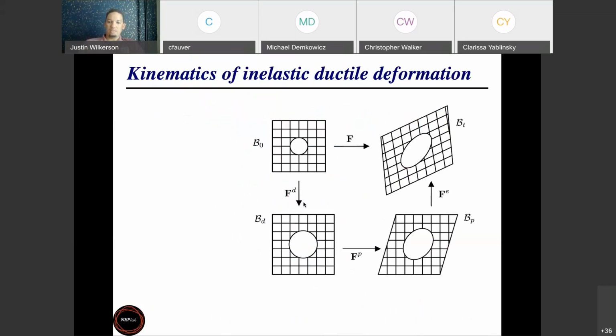And then just to make the connection again, the last point I want to make is that the kinematics are actually really important when it comes to dynamic deformation of materials. Many constitutive models for quasi-static failure of materials will account for these first two aspects, that the elastic constants are degraded by damage and that the strength of the material is degraded by damage. But they won't often be as careful with the kinematics. As you grow voids, you are introducing inelastic volumetric strain into the material, and that needs to be accounted for. That's going to affect your wave propagation.